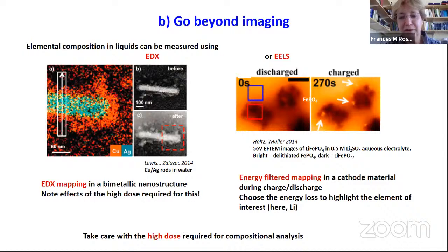Go beyond imaging. This is the same compositional mapping example that I showed earlier, where you can try and look at the chemistry changes during battery operations. Here's an example using energy dispersive X-ray mapping, and you can see the difference in composition of this object. But there are a lot of electron beam effects, at least in this experiment, because a very high dose is required for compositional analysis.